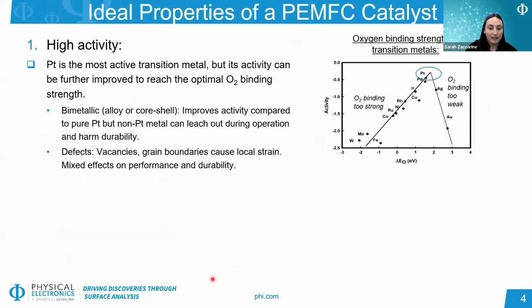So when we think about the ideal properties that we want in this type of catalyst, again, as I mentioned, of course, we want high activity, we want a high performing catalyst. Platinum is considered the most active metal towards this reaction. And if we look at this plot on the top right, this is looking at the oxygen binding strength of a variety of different metals. This is colloquially known as a volcano plot due to its shape. And you can see platinum is the closest metal towards the peak, which is why it's commonly used. However, it's not quite at the peak.